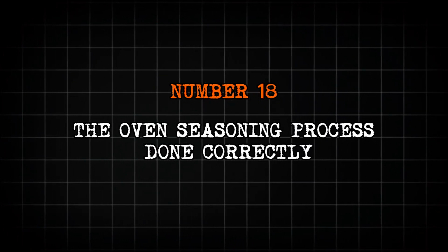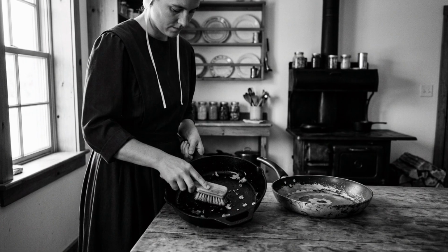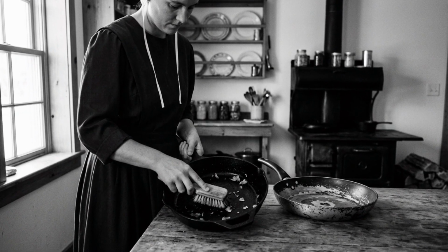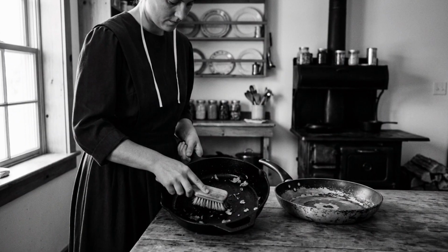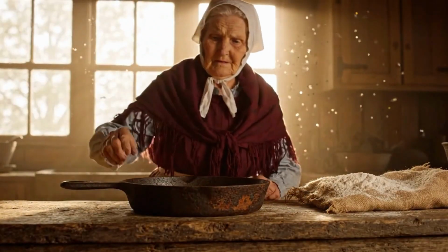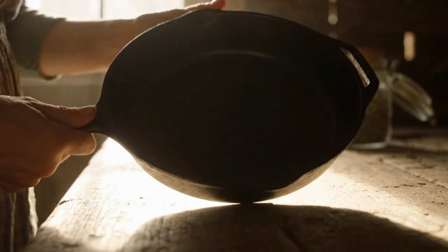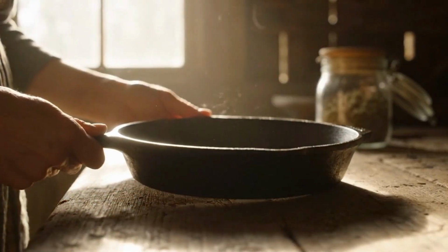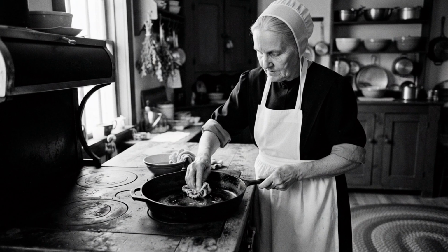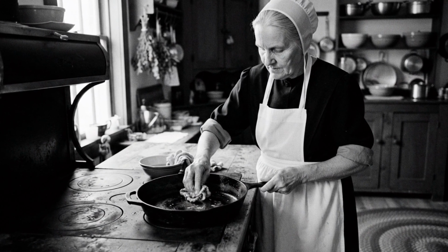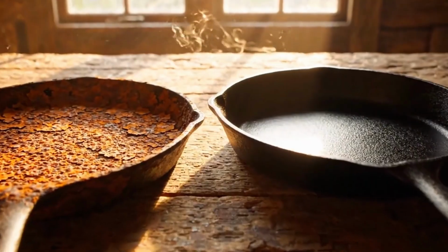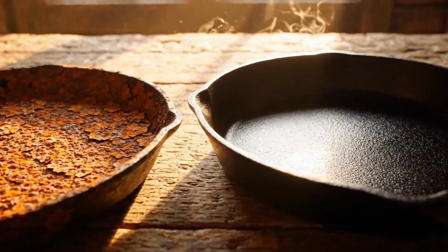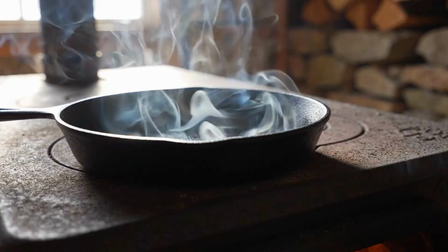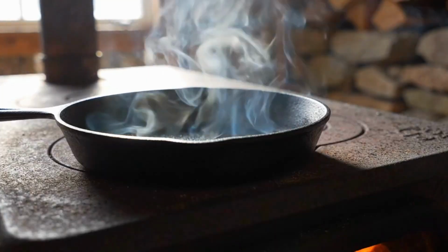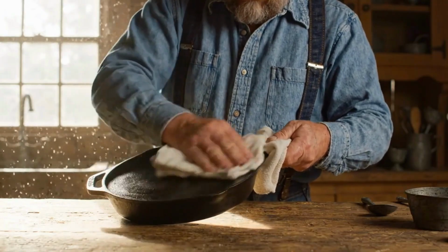Number 18. The oven seasoning process done correctly. Here is the exact process that an Amish farmhouse kitchen uses to season or re-season cast iron, and every detail matters more than it might seem. Preheat your oven to 500 degrees Fahrenheit, or as close to it as your oven will go. Apply a thin coat of flaxseed oil to every surface of the pan, inside, outside, handle, and all using a cloth or paper towel. Then take a clean dry cloth and wipe off almost all of what you just put on. The pan should look almost dry rather than visibly oily.